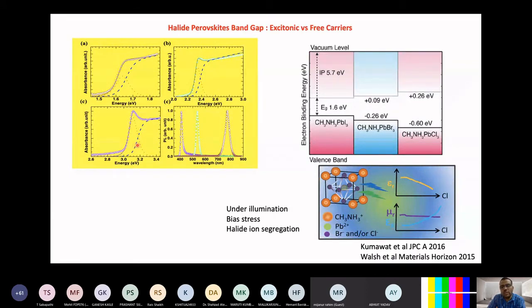So this is what is shown here, and we could demonstrate that this all happens because the dielectric constant of the system changes. It goes down as we have more and more chlorine coming into the picture. These are the data for MAPbCl3, MAPbBr3. You have the CH3NH3, you have lead, and you are changing bromine and chlorine. As you increase the chlorine concentration, your dielectric constant goes down, and as the dielectric constant goes down, exciton binding energy increases.